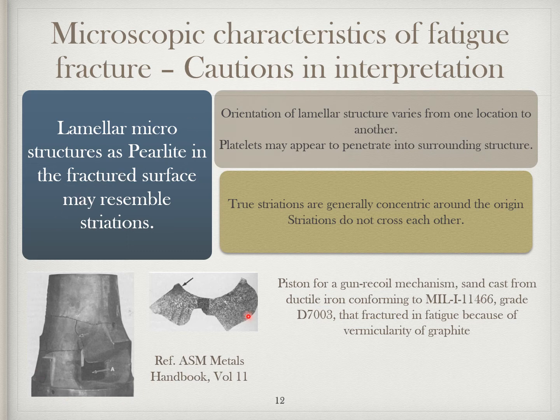The figures shown here are that of the piston for a gun recoil mechanism sand cast from ductile iron grade D7003 that was thought to be fractured by fatigue because of the vermicularity of graphite. Because some of the pistons exhibited regions with an appearance suggesting fatigue, SEM factographs were prepared to attempt to locate fatigue striations and to estimate the number of cycles to failure. These factographs showed configurations similar in appearances to fatigue striations, but it was concluded that they were perlite lamellae because the spacing agreed with the perlite dimensions observed in optical microscopes.